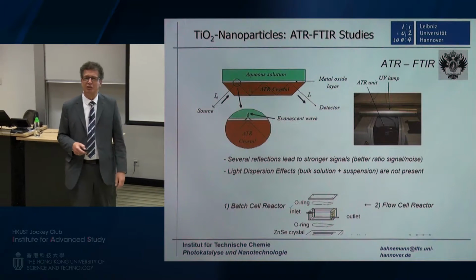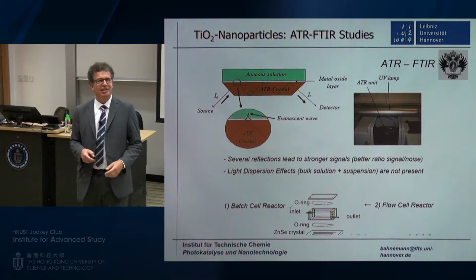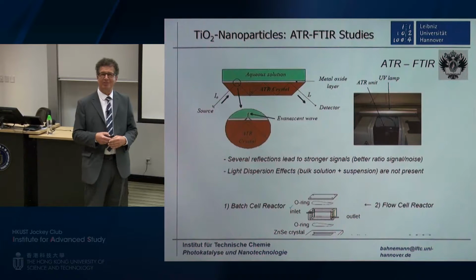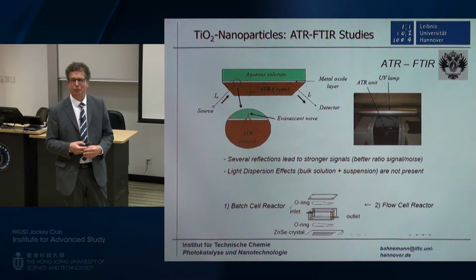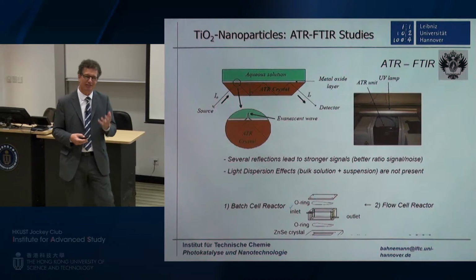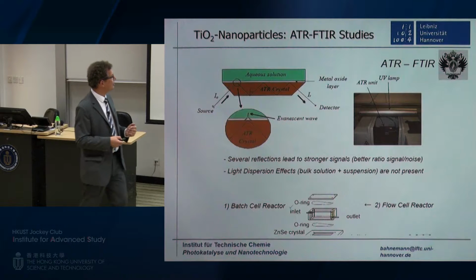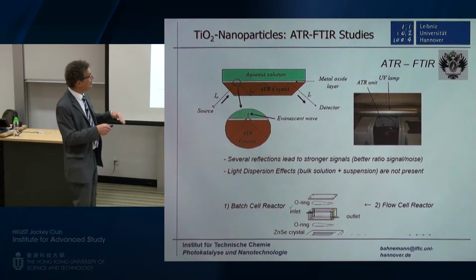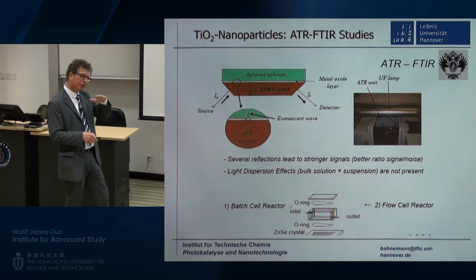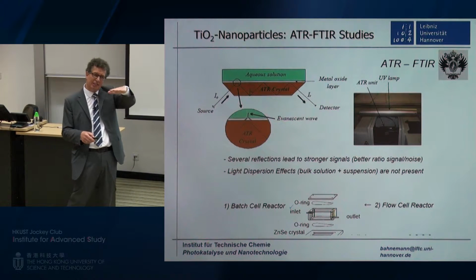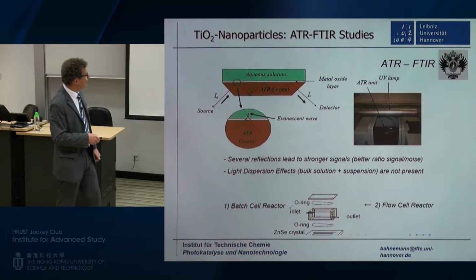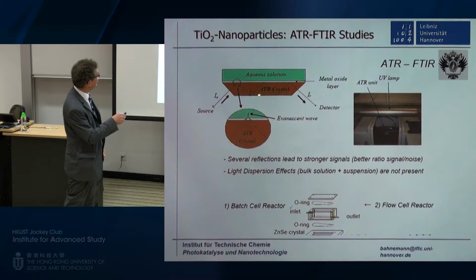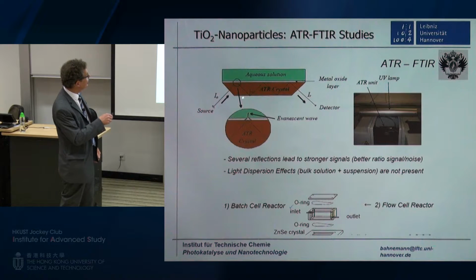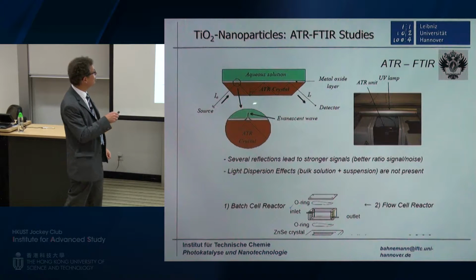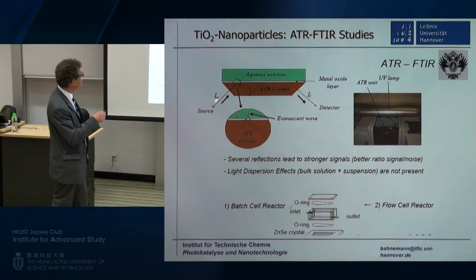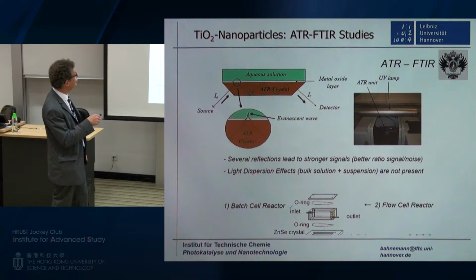Now I'd like to talk about the results of an experiment which is actually only done as a blank experiment. But sometimes it's interesting, well, first of all, one should always do blank experiments, but sometimes it's interesting to try and understand what was the result of this blank experiment. And here we did the blank experiment when we investigated with infrared spectroscopy the surface, the interface between the TiO2 and the water layer. You do this in a setup where you use an ATR, which stands for attenuated total reflectance, infrared crystal, where the infrared light penetrates like this through the crystal.